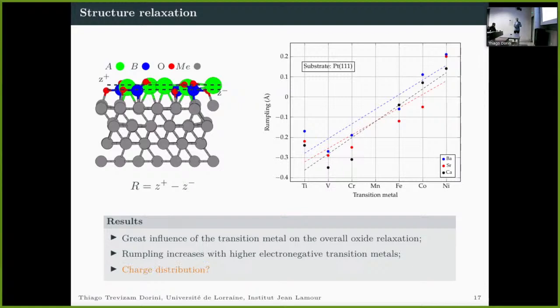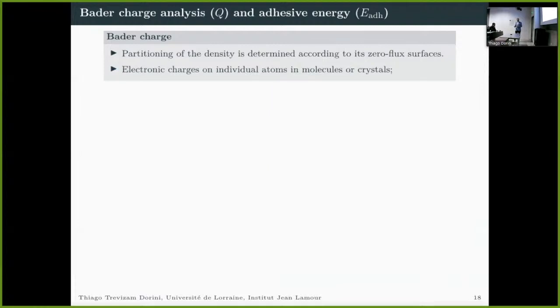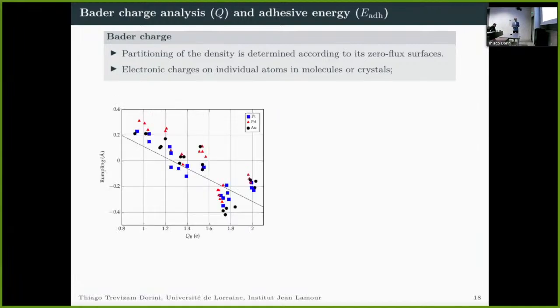And this may correspond also to an increase or a very different set of the charge distribution on these compositions. And we'd like to measure this with a methodology that's called the Bader charge analysis. In this analysis, what we do is partition the density according to zero flux surfaces. And in this methodology, we can have the electronic charges on individual atoms on these oxides.